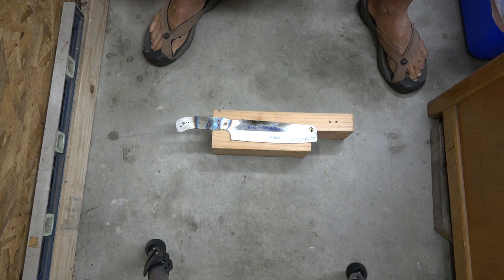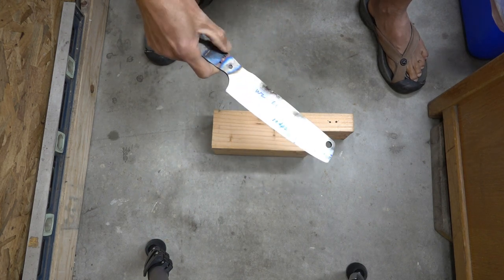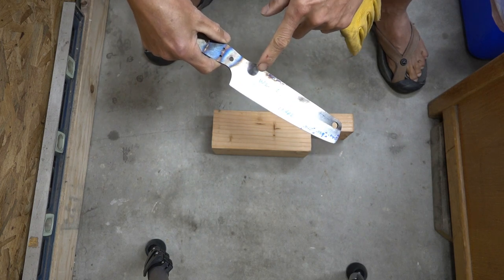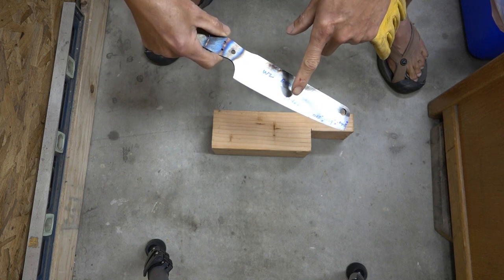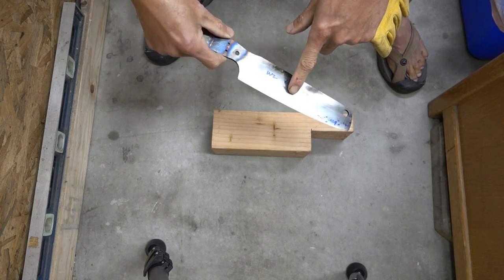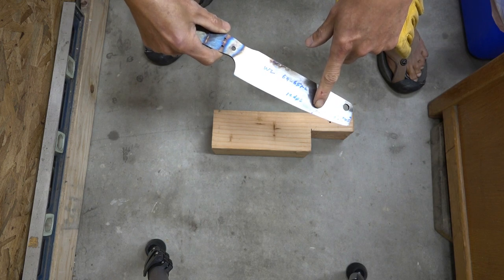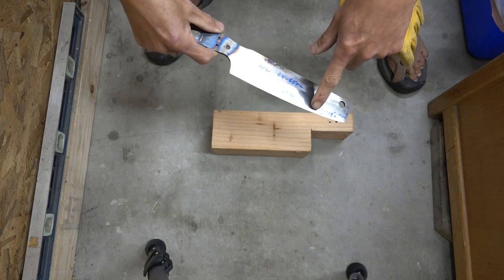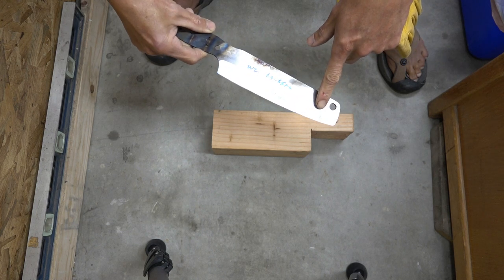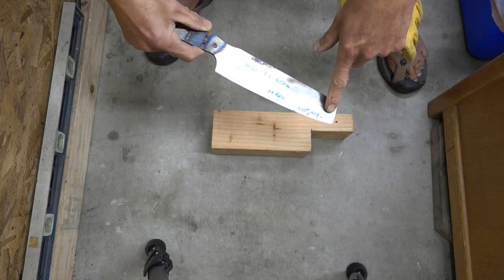Plant Cut Metalwork. It's Saturday, May 18, 2019. I have a butcher and cleaver knife here. I made it out of W-2 steel. The Rockwell hardness is between 64 and 65. The sharpening angle is 18 degrees per side. Thickness behind the edge at the sharpening bevel is 15 thou. 0.8 inches up from the edge is 29 thou. 1.25 inches up from the edge is 45 thou.